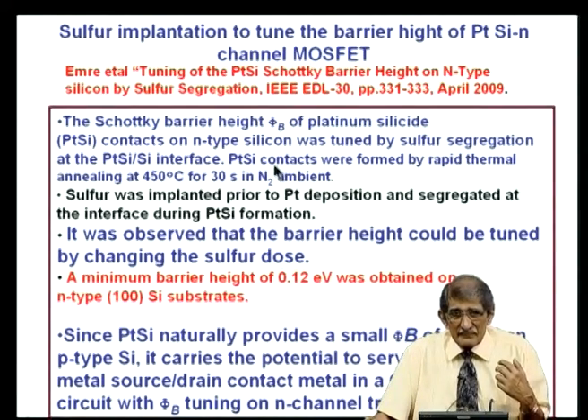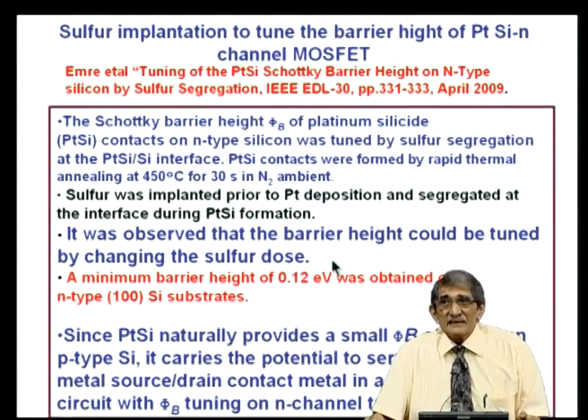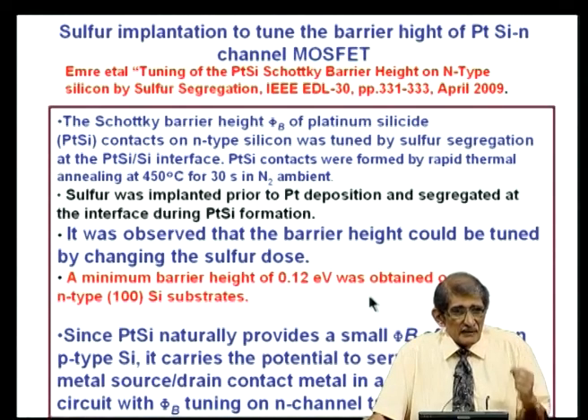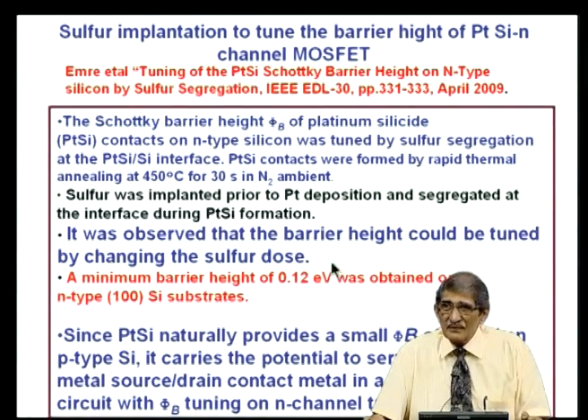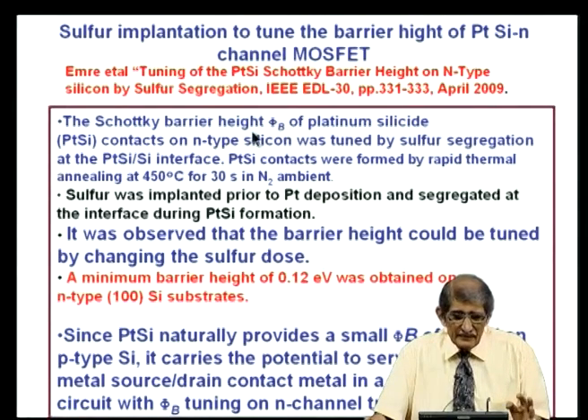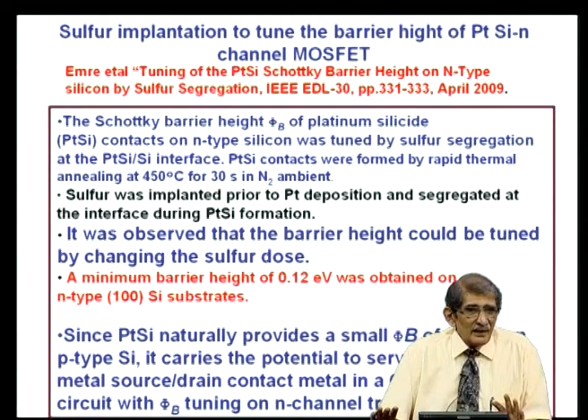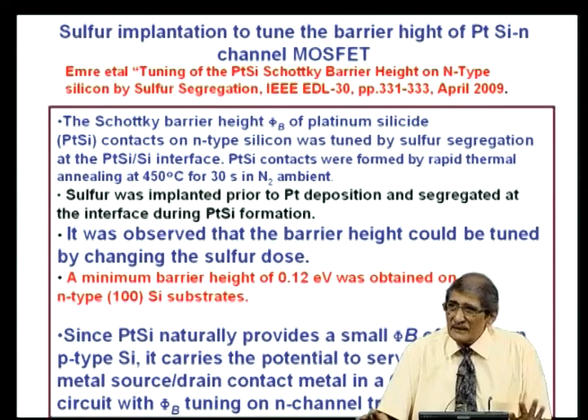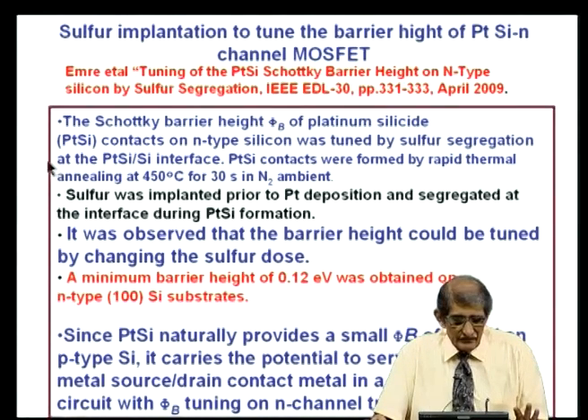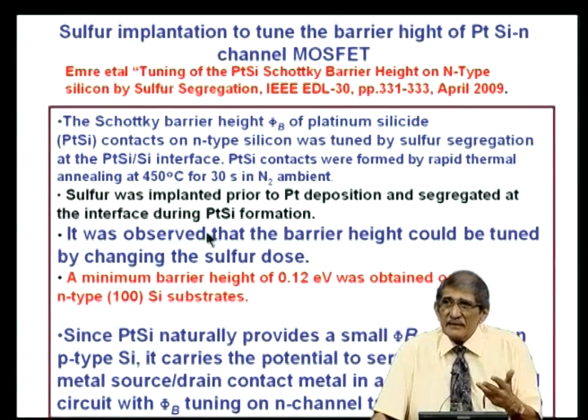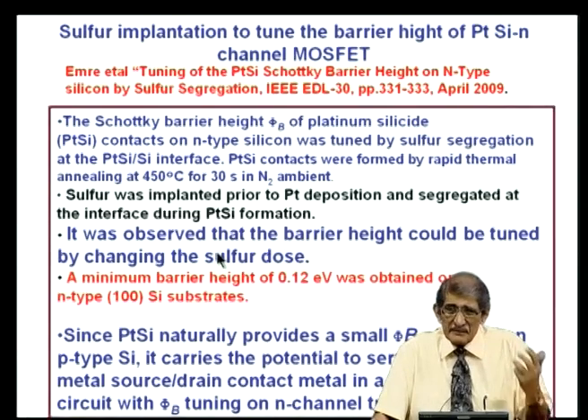So, if you want to make CMOS, you must have the ability to overcome this problem, not by adjusting the work function. You must have the ability to have both ΦBP under your control and ΦBN under your control. So, if I am using platinum silicide as contact, I can make a p-channel MOSFET without any difficulty, because barrier height is very small, 0.24 electron volt. Even in germanium, I can make it very small.